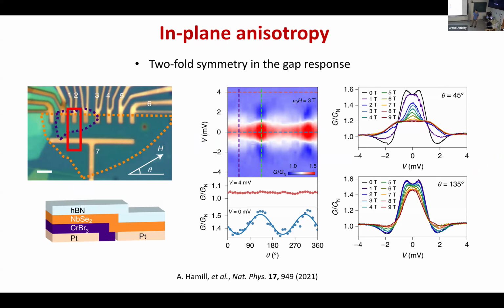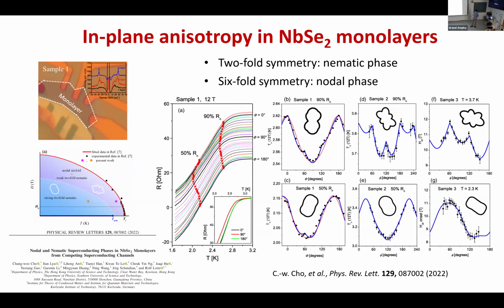Is it possible to have a flux line running through the thin edge of a monolayer? Because flux is rather extended. Yes, it depends on the material. Exactly. If it's just a monolayer, I would say it's really hard to imagine how it goes through. But for several layers, a tri-layer or bi-layer, then you can go through. There's another effect that sometimes people talk about, that these 2D monolayers are never really flat. Exactly, I mentioned this too. Nobody has mentioned this effect so far. I haven't found any literature, but I know some people working in this field are talking about this effect, and they're trying to prepare some papers on that.